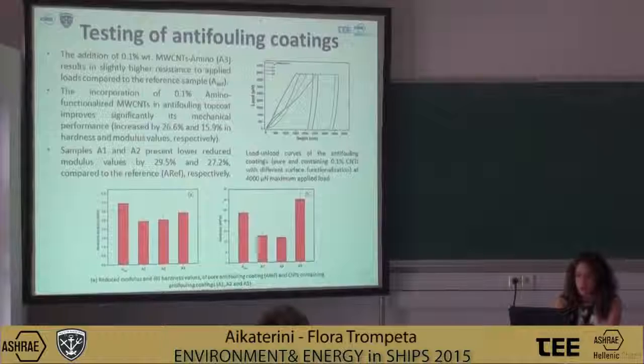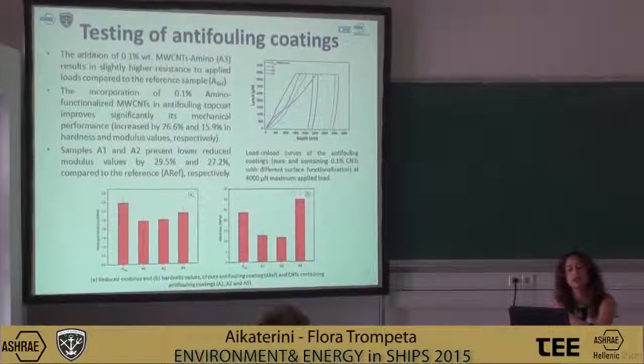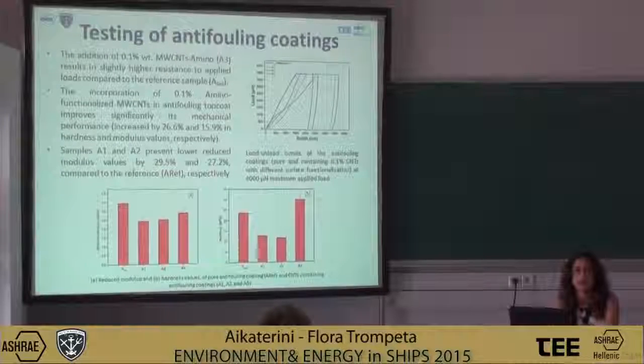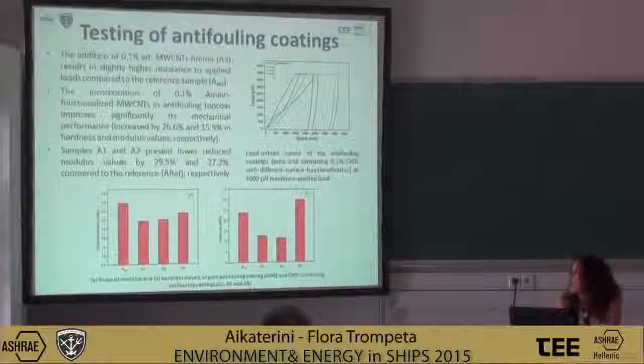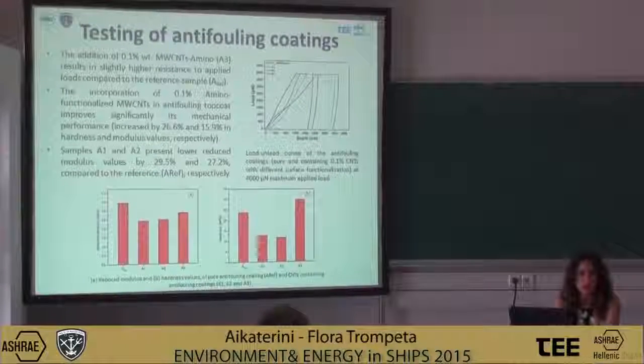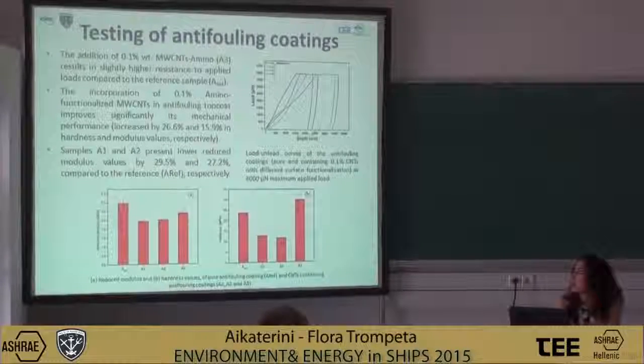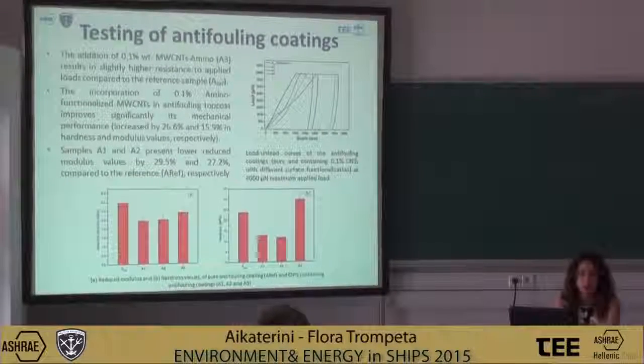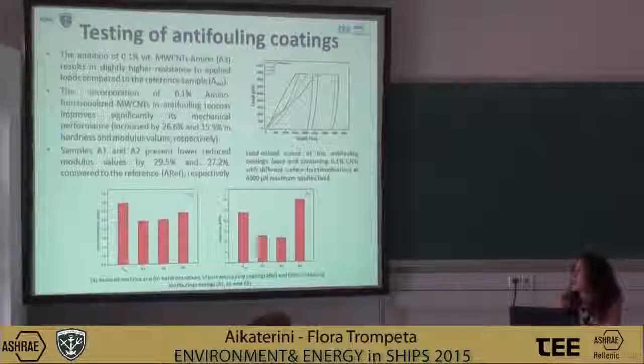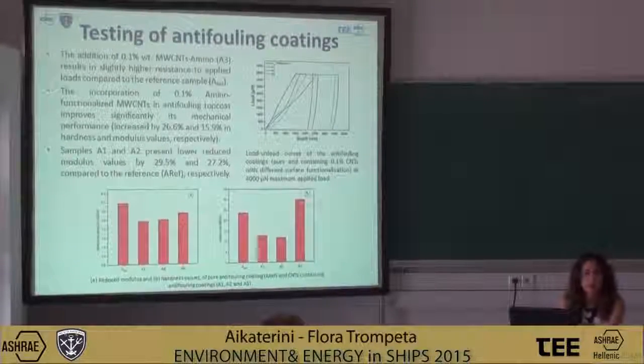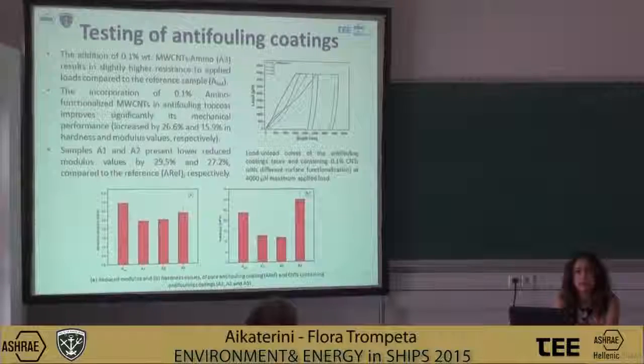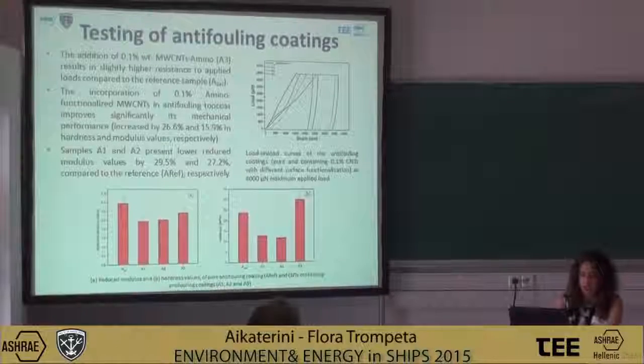About the antifouling coatings, we had different results. Firstly, the addition of 0.1 percent multi-wall CNTs with the amino functionalization resulted in slightly higher resistance to the applied loads compared to the reference sample. That means that we have an improvement in the mechanical properties of this coating. Also, the incorporation of the same material in the antifouling top coat improved significantly its mechanical performance, with an increase of around 30% in the hardness and 15% in the modulus. Whereas samples A1 and A2 presented a lower reduced modulus by around 30%. That's because we have not very good compatibility between the carbon nanotubes and the polymer matrix, if they are pristine or if they have the carboxyl functionalization.